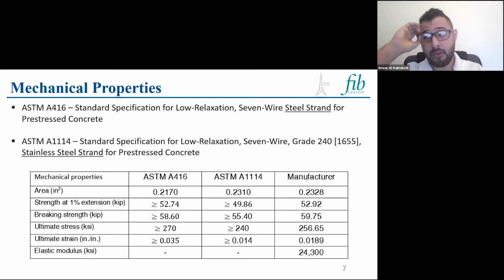Sometimes the design is not controlled by the strength. So if it's controlled by service, you will add more strands. And then in this case, you will have many stainless steel strands where you can achieve as close deflection to those prestressed with carbon steel strand. I see your point. Yes, it's an issue and we're working on that.